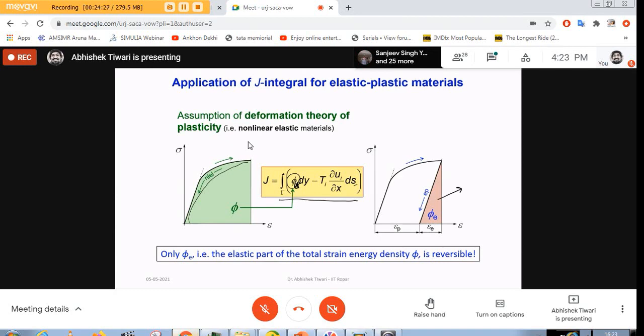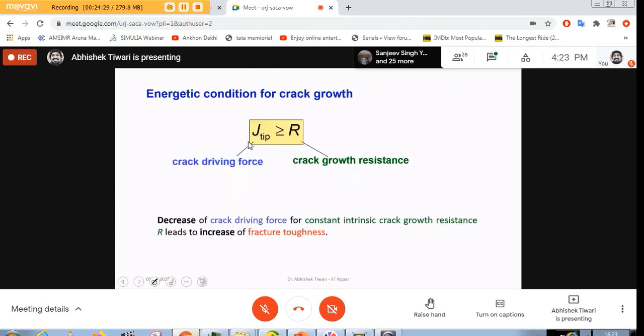So the solution which we are proposing, before that we need to have something in our mind. We have talked about what is the problem with the J integral, and then let us understand this, that the amount of energy which is available at the crack tip, which is the true crack driving force, let us call that J integral. The conventional J integral is having some problems that we have discussed. This crack driving force which is available at the crack tip, if it is greater than the resistance which material is offering, then crack will grow, and if it is lower than that, then crack will not grow. This is not very hard to accept.